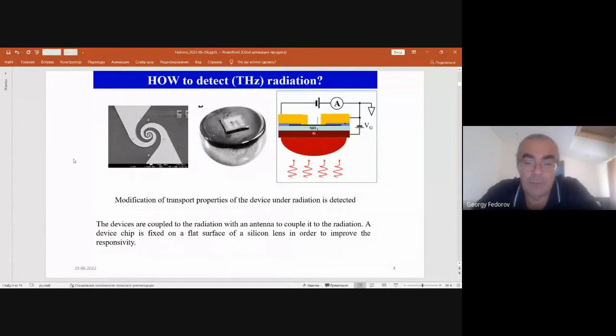So we have something, which I don't show at the moment, embedded into a terahertz antenna. This antenna is on a small silicon chip, which is in turn located on a silicon lens to couple whatever you have inside the antenna to the terahertz radiation. With such a setup, you can work with very tiny objects that have dimensions of less than 1 micron, but you still can probe their response to radiation, measure the photoresponse spectrum and do many other interesting things. But the first thing you do is you start with measuring the